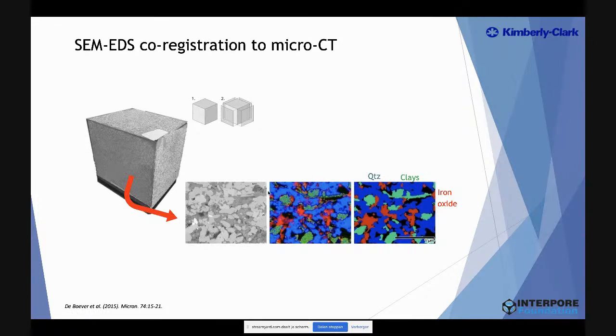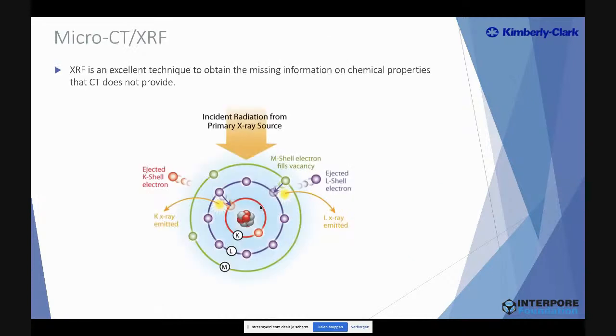You try to get the mapping of all your elements, of all your minerals, and then you combine this with the gray values of your X-ray CT system, and this allows you to get an indication of the composition. Another thing you can do is combine micro-CT with XRF, as XRF is an excellent technique to obtain some missing information of chemical properties that CT does not provide.